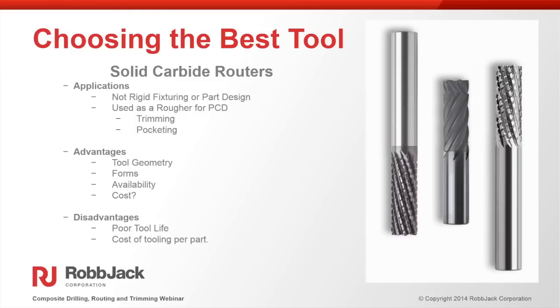If you have a rigid application, you don't have to do that. You can come right in with a PCD or diamond-coated tool and cut in one shot, and you don't have to do that roughing and finishing application. But one of the things we'll get into further is that a lot of people will apply carbide tools they're used to using at high RPMs and slower feed rates, and it tends to be more of a grinding operation. But when you go over to the PCD or diamond coating, you have that wear resistance, and you don't want that high RPM, slow feed rate application. You want to get in and out of the cut as fast as possible because now you have sharp cutting edges, and it tends to not be as much of a grinding operation.